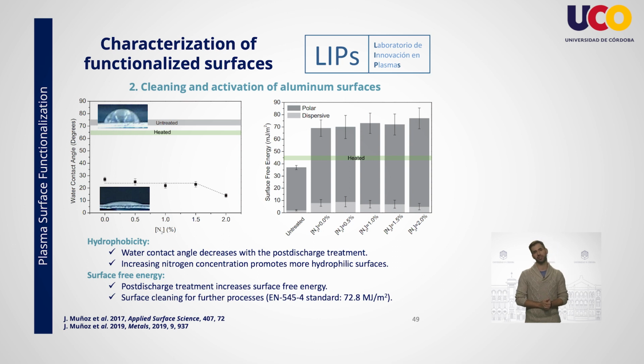One might wonder if the temperature is responsible for surface modifications. To check this hypothesis, the aluminum surface was exposed to external heating. The information obtained after heating is represented in the figure by a horizontal green bar. As it can be seen, there are only small differences in comparison with the untreated samples. Therefore, we can conclude that temperature is not responsible for the surface modification, so it has to be related to chemical modifications.